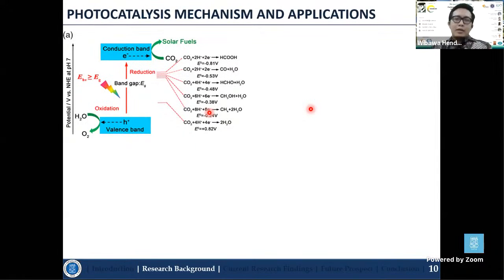In principle, briefly, the mechanism of photocatalytic technology is, first, light, whether UV light or visible light, is irradiated onto the semiconductor-based catalyst with an energy higher than the band gap energy of the semiconductor photocatalyst, and it will stimulate the electron excitation from the valence band to the conduction band. When the electron is excited to the conduction band, the electrons and holes perform the reduction and oxidation reactions. For instance, in photocatalytic carbon dioxide reduction, carbon dioxide is reduced in the conduction band to generate products such as formic acid, carbon monoxide, formaldehyde, methanol, methane, and so on. While in the valence band, water will be oxidized to generate oxygen.